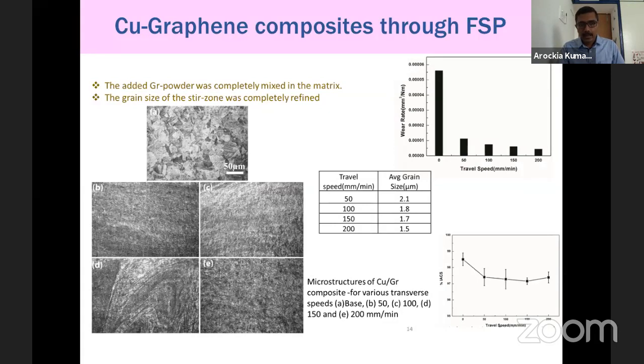In this case, after doing FSP, what you are seeing here is a very coarse microstructure, around 40 micron grain size before FSP. But after doing FSP, the grain size is reduced to somewhere around 1.5 to 2 microns, and it depends on the travel speed. What we did was vary the travel speed and fix the rotational speed, and thereby we studied how FSP affects the grain size, and at the same time how effective it is in distributing graphene. Through Raman spectroscopy, we confirmed that graphene is uniformly distributed in the stir zone, and the grain size reduced from 40 micron to a minimum of 1.5 micron.